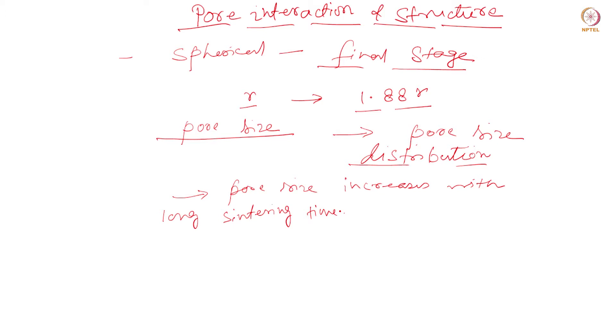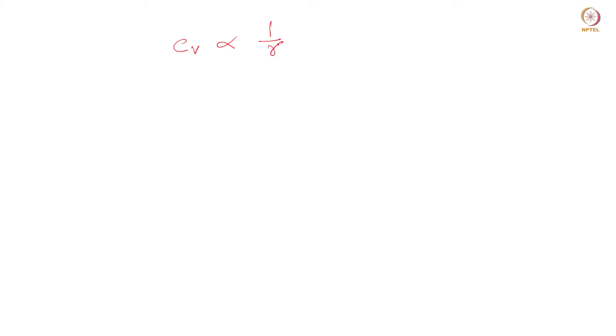Since there are both smaller and larger pores - as there is a distribution in pore size - the smaller pores will emit more vacancies than the larger ones and therefore will also grow in size, because the local vacancy concentration is inversely proportional to the pore radius. So if Cv is the vacancy concentration, then Cv is proportional to 1/R.